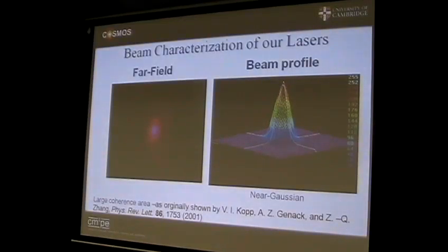You know, if you make a classical Nd:YAG system, if you want to do mode selection, you have to put spatial filters into the cavity. The focusing of the pump beam gives the pinhole effect, if you like, or the spatial filter of the material itself. And then if you go to the far field, you can actually see the Airy ring patterns of what that beam looks like. So you're getting, in a very simple film, a chiral nematic liquid crystal with a fluorophore in it, and you're pumping it with a focused laser beam, you're getting virtually TEM00 output. That gives you a large coherence area, which is what this really shows you.